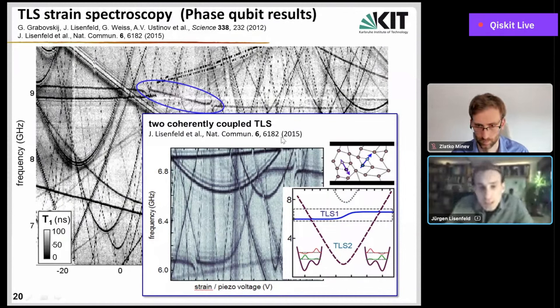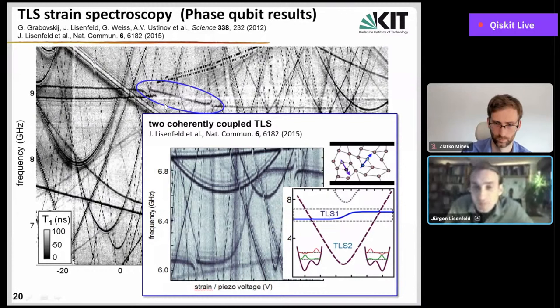What we now see in the signature is the resonance of a certain TLS called TLS1, which by itself does not couple so much to the strain, so you just see basically a horizontal line here. But there's a second defect, TLS2, which you can tune by the strain and which we can also tune through its symmetry point. If you do this, then the location of the ground state changes from one well to the other well.